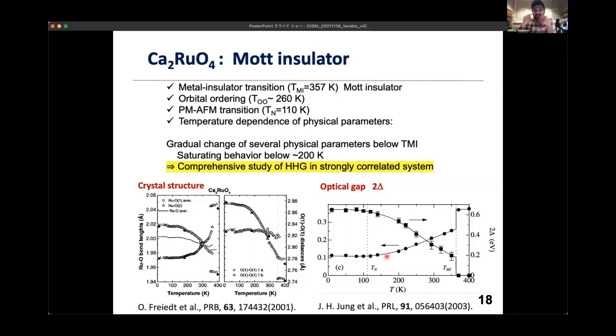But I mean, I don't care what the incoming beam is. I just want the outgoing HHG to be a circularly polarized beam, not linear. In the case of threefold symmetry, we can obtain second harmonic under excitation with circularly polarized light. So that quite depends on the crystal symmetry. If the system has threefold, 120-degree symmetry, we can expect the second harmonic. Okay, thank you.